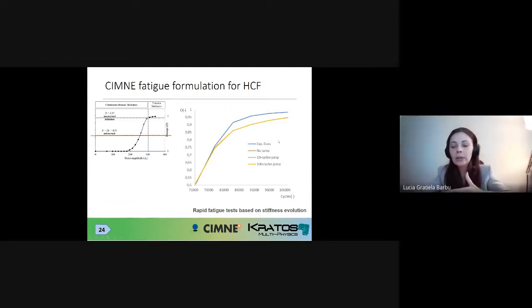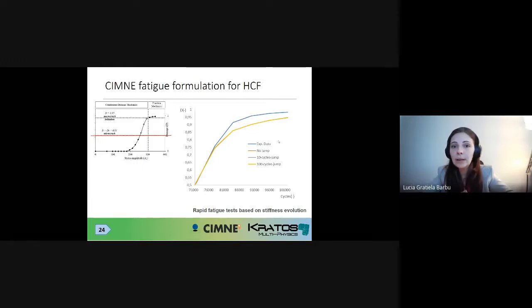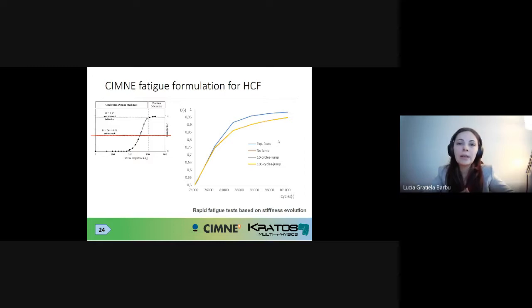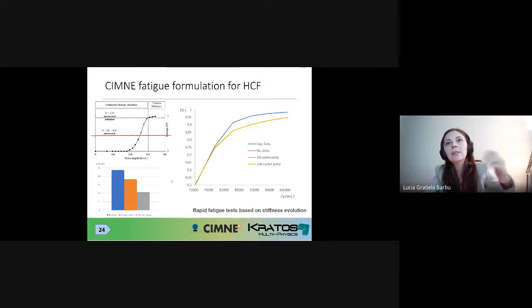And we've also had the opportunity here to test a cycle jump algorithm, which we developed quite some years ago, that helped us significantly reduce the computational time of high cycle fatigue simulation. Why? Because when you do this simulation, applying the load for hundreds of thousands of cycles, cycle by cycle, you are going to be spending a lot of time, basically about 24 hours. We wanted to see what happens when we use cycle jump strategies. How are we able to reduce the computational time? You can see here, for instance, with a cycle jump step of 100 cycles, we are managing to lower the computational time to 10 hours. And this analysis can be further pushed down in terms of computational time.